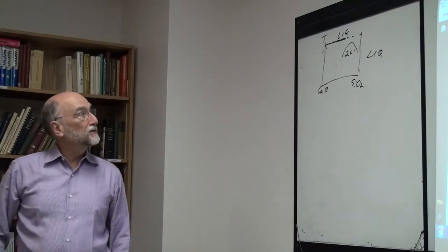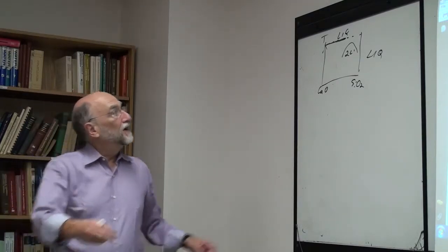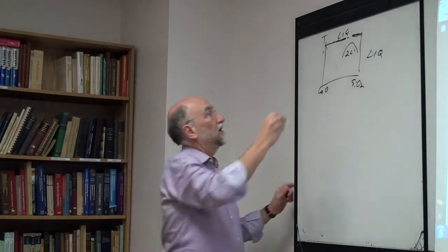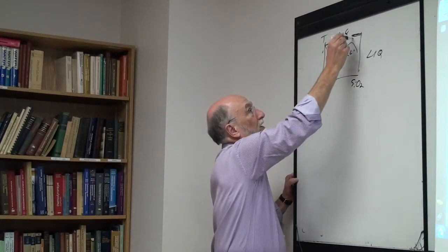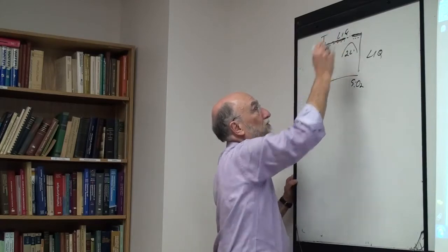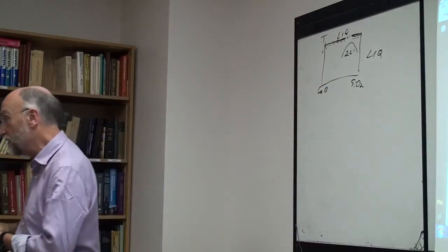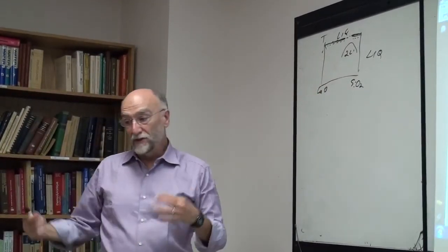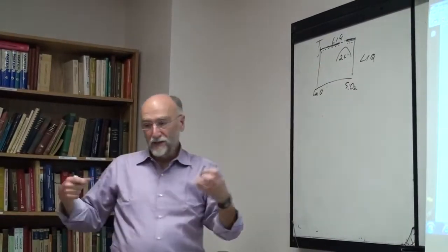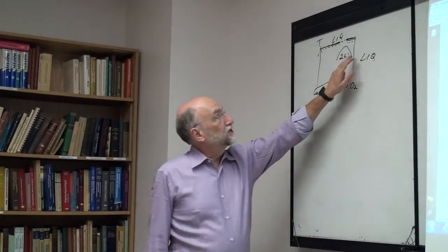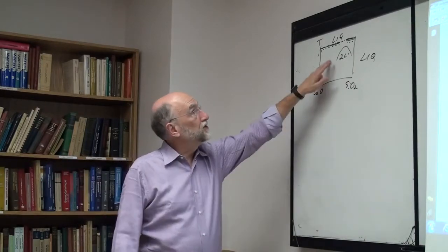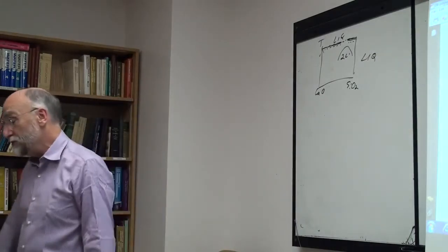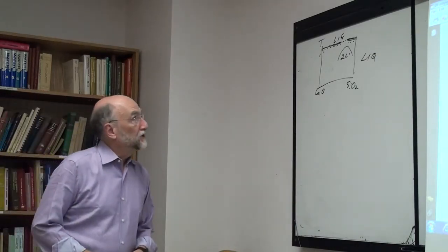We'll talk later about slags, but it's an orthosilicate. And over here you have a very different structure, a polymeric silicate network. So you have a local structure over here and another different local structure over here, and then of course there's a transition region where the two structures come together. Because of this, you actually have two liquid regions at low temperatures. Rather than have this transition region, which is hard to fit everything together, the system at lower temperatures simply prefers to split into two phases, one with one sort of structure and the other with the other. But as you go to high temperatures, above the critical point, you do have a complete liquid solution.